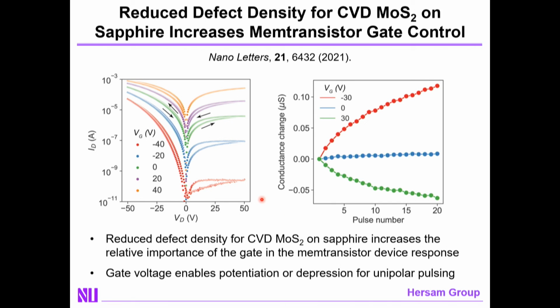So for example, if I take a MEM transistor made from chemical vapor deposited MoS2, and I grow it on sapphire compared to growing it on silicon dioxide, on sapphire, you get a much lower defect density. That will imply or should imply that your memristive response is attenuated, and that's indeed the case. We see smaller memristive loops here.